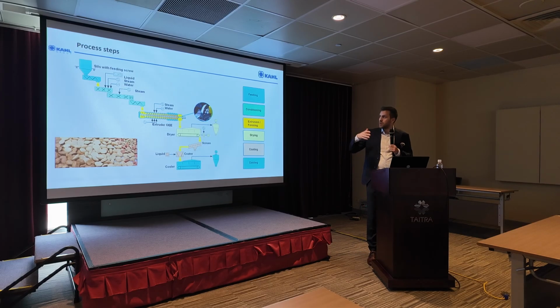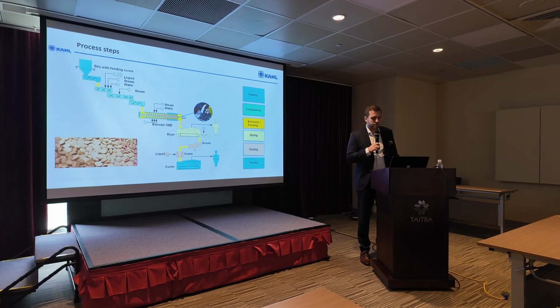Here, Amandus Kahl is using a double conditioning setup. So we want to go up to 95 degrees. Of course, depending on recipe, maybe 80, 85 is also sufficient. And we use these two different types of conditioner before our extrusion. And here we even have implemented another equalization screw after the conditioning.